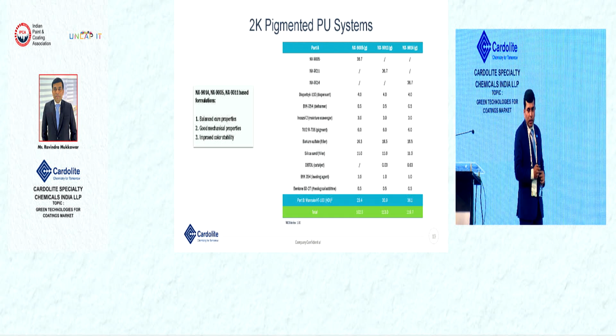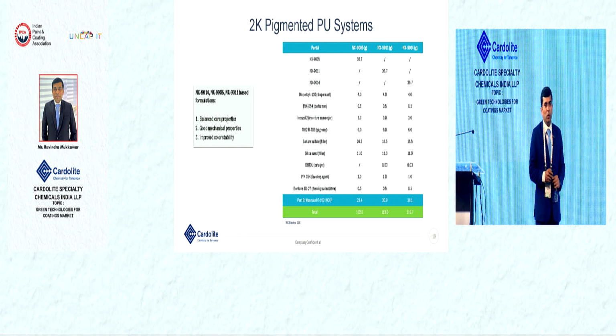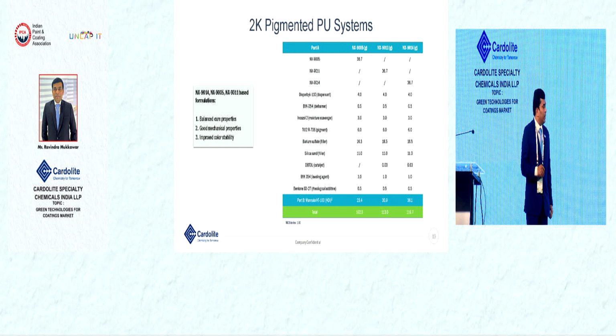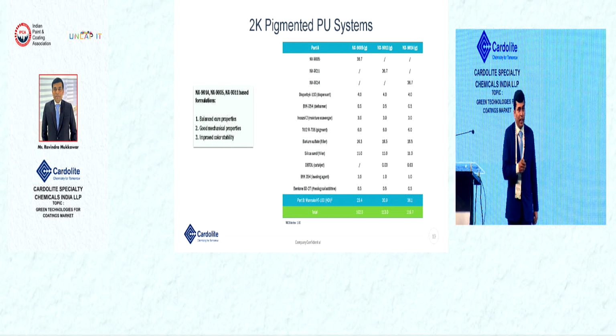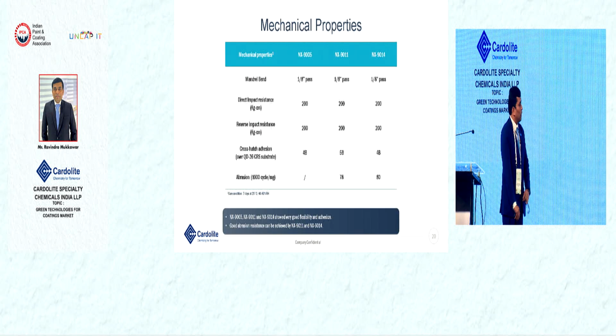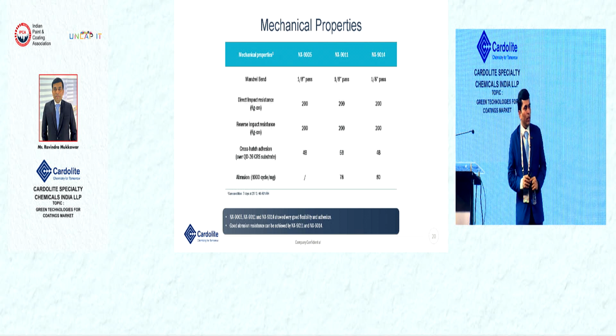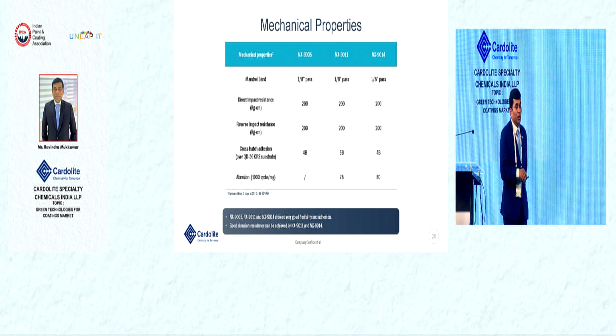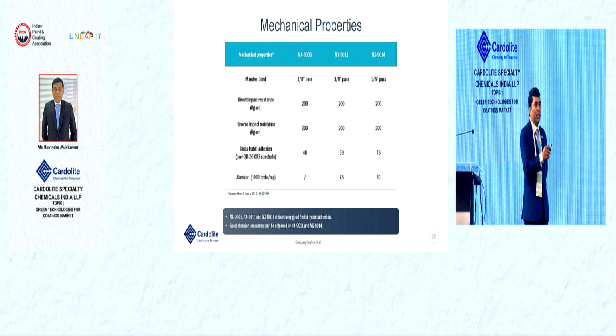This is another formulation we developed using 9005, 9011 and 9014. 9014 is for exterior, which will be HDI based, which will give good weathering properties for exterior application. We checked the mechanical properties and it passes 1/8 conical mandrel, gives a good direct impact test, and has good abrasion resistance. This is one of the important factors in PU, because you need good abrasion resistance, and wear and tear will be less compared to the epoxy system. So that's the reason the industry is moving from epoxy to PU in some application areas.